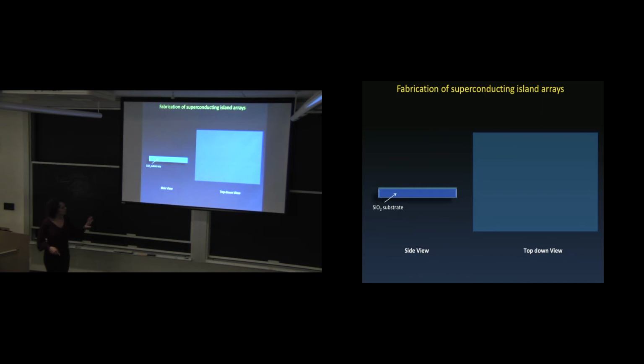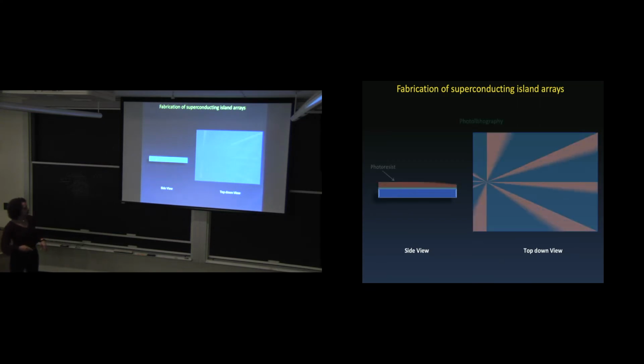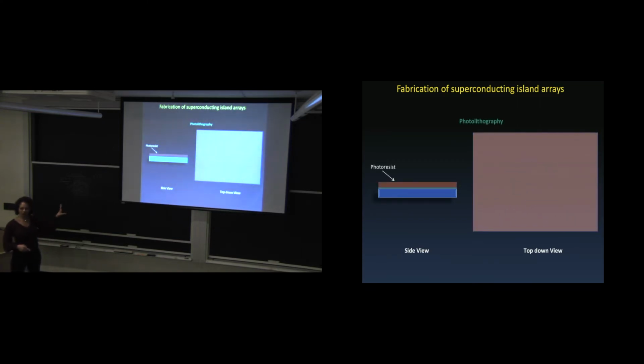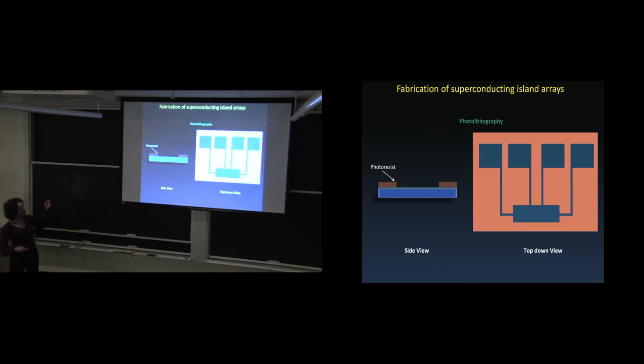Okay. For people who don't do lithography, we make these lithographically. Here's a very quick animation of this. We start with a silicon oxide substrate. We spin on a photosensitive material. We expose that material to light and then develop it, in which case the photosensitive material comes off, and we're left with a pattern in the shape that we want. This is our 4-point measurement pattern.